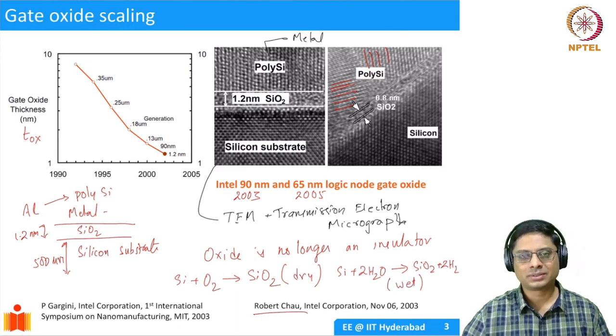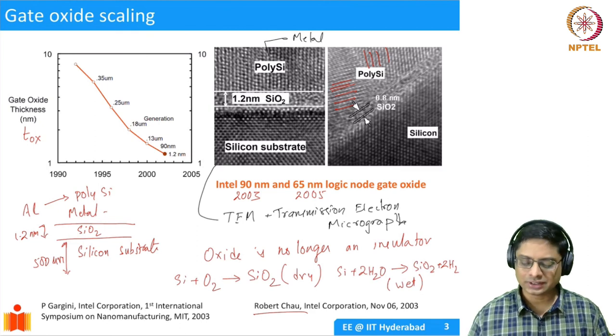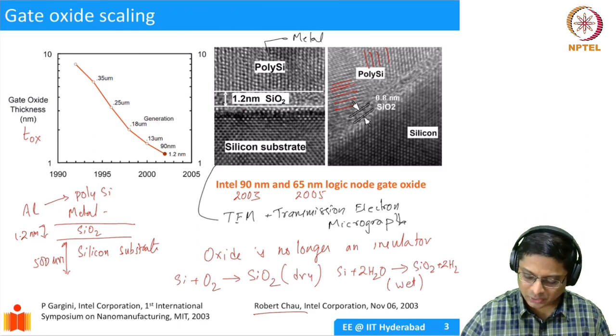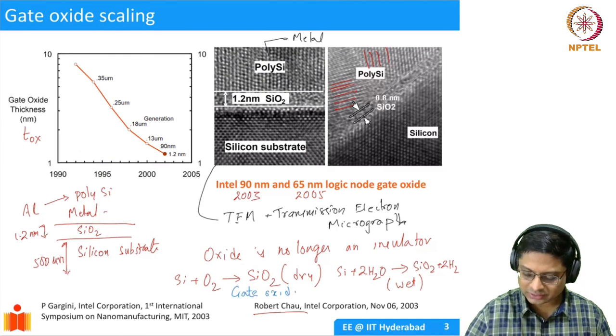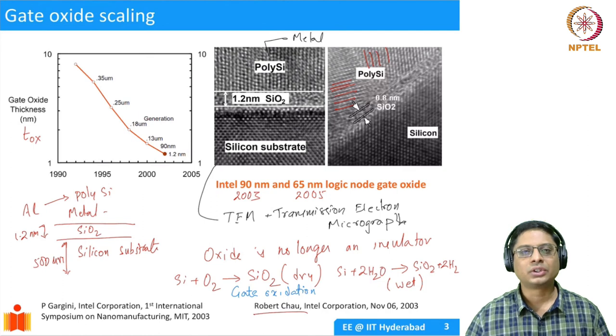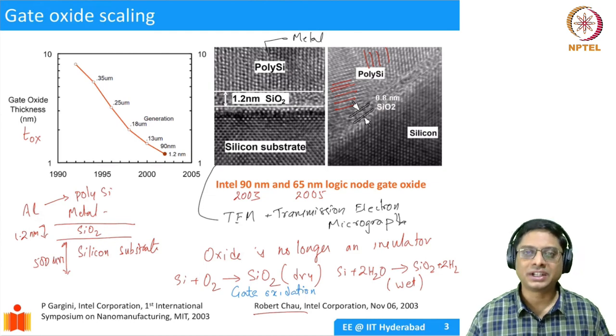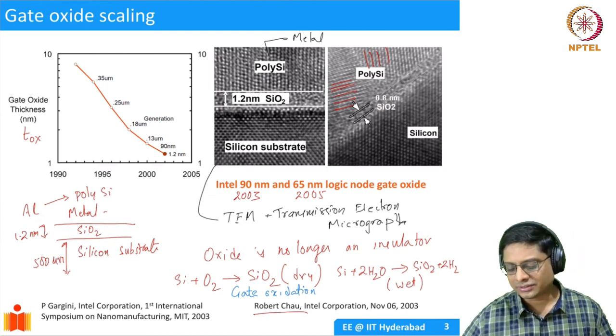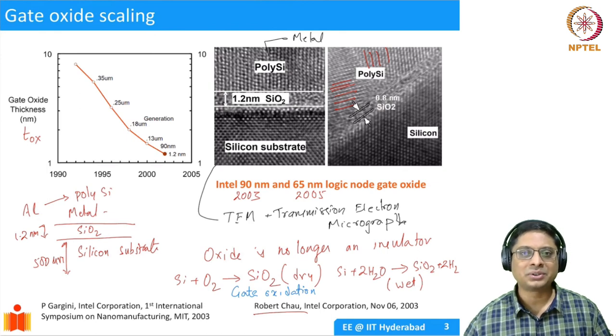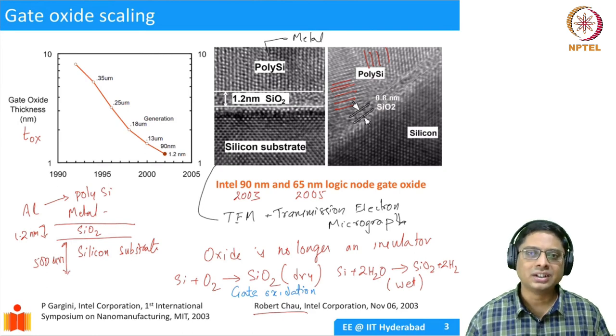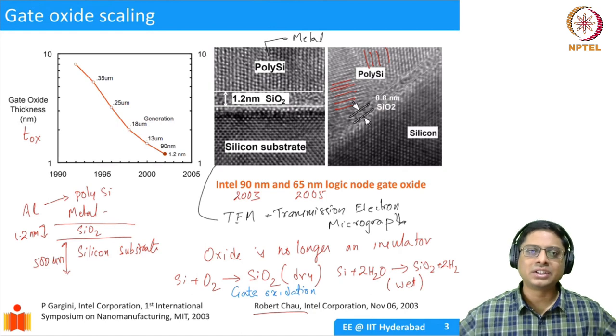If you study the various technologies, they will tell you that gate oxidation is done by the dry oxidation process. If you just pass dry oxygen, no water vapor, you get very high quality oxide. Whereas wet oxidation gives low quality oxide, but you can get a very thick oxide. Dry oxidation is a very slow process, so you can't make a very thick oxide. But in the gate, we just want 1 nanometer oxide, so dry oxidation is perfect for that. Using dry oxidation, we make this oxide on the silicon wafer, and then you deposit metal on top of it. That's how you make a MOS capacitor.